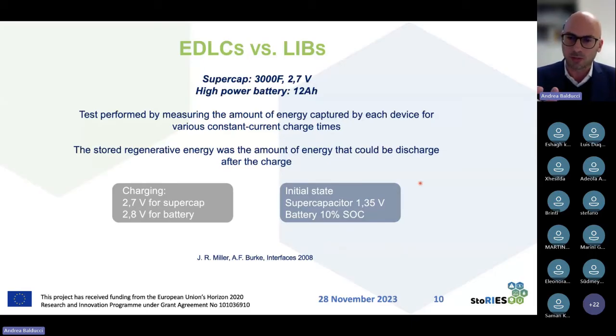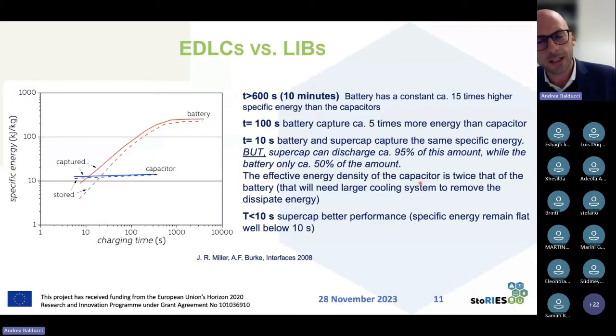So basically, the goal was to understand what you can really give back after you charge the system and use it. They were, as I said, using a supercapacitor working at 2.7 volt. The battery had a potential cell voltage of 2.8 during charging. The initial state of the supercapacitor was 1.35 volt, and the battery was at 10% state of charge. What you can see here is the result of this comparison. It is a graph with the charging time in seconds and the specific energy. This graph is quite interesting because it immediately shows us the differences between these two devices.